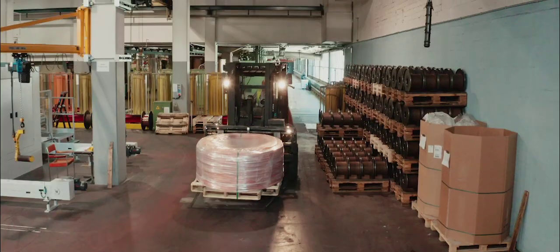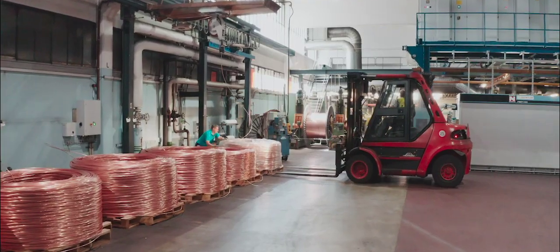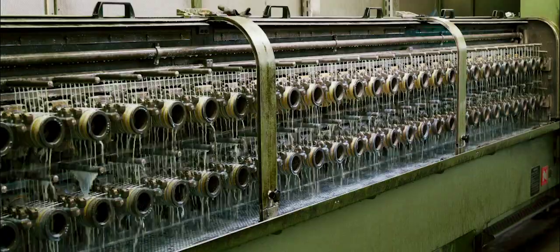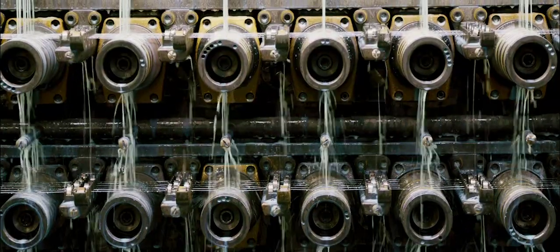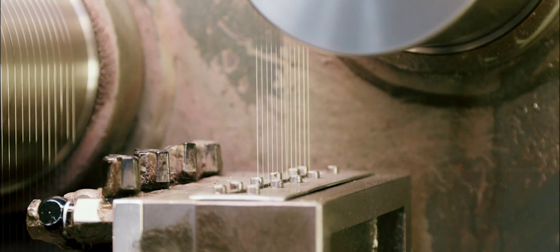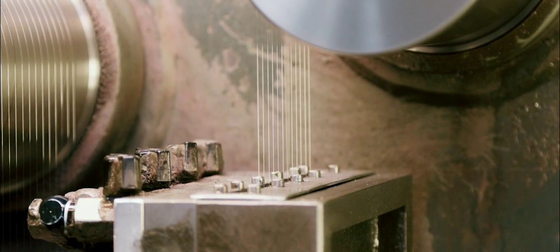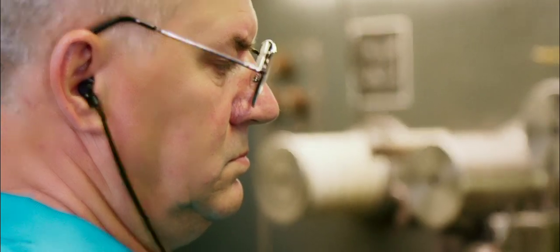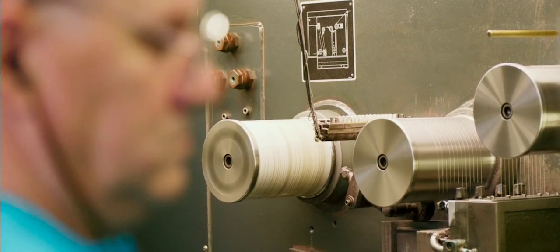For the production of our copper cables, 5,000 kg copper rod with a diameter of 8 mm are purchased. On various drawing plants, a final diameter of as little as 0.1 mm can be drawn. Stranding machines can produce flexible conductors with various numbers of wires, diameters, and lay ratios. This step of the process requires a flawless initial product in order not to affect the following processes.